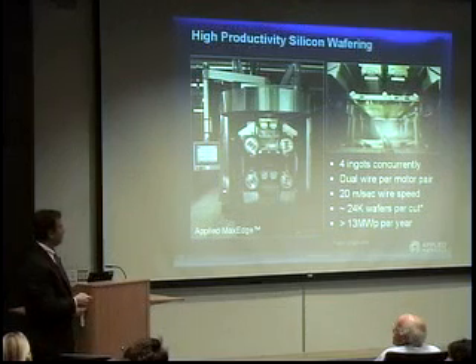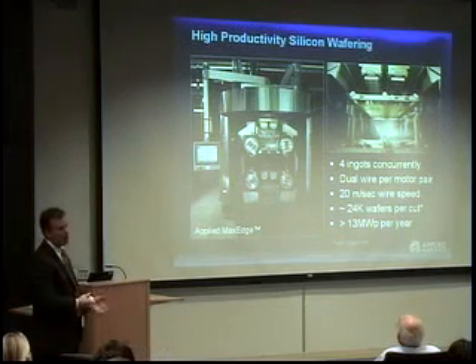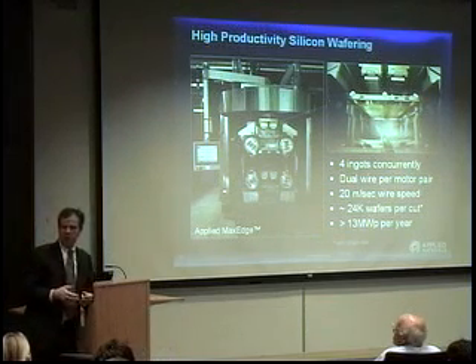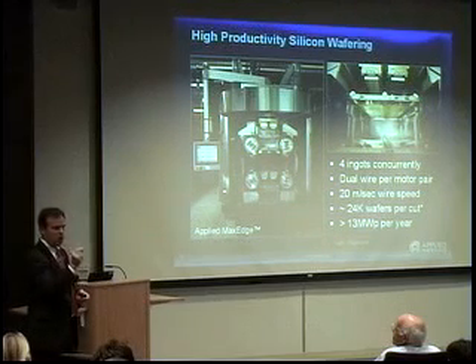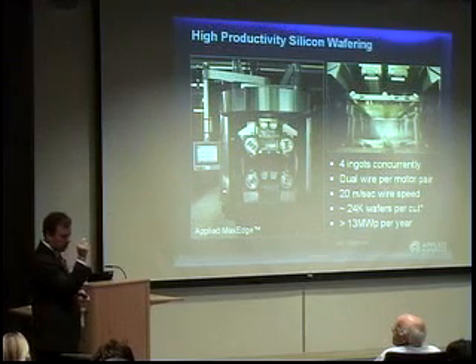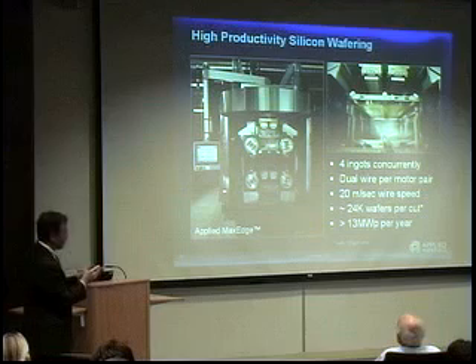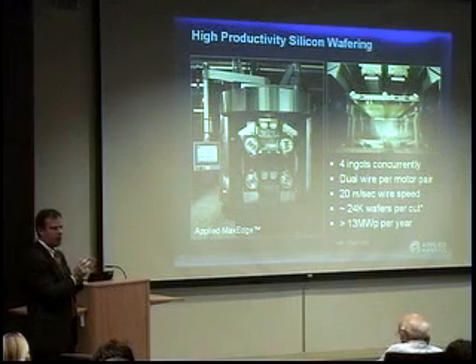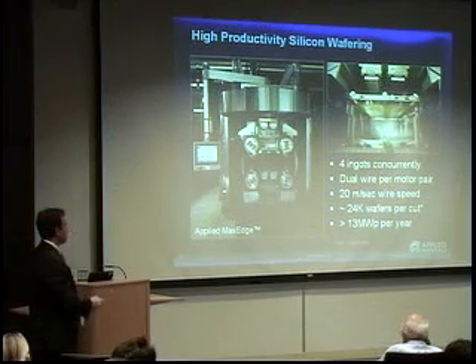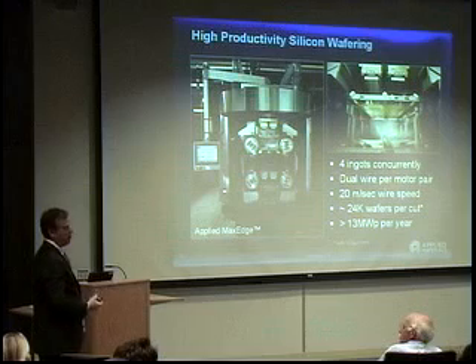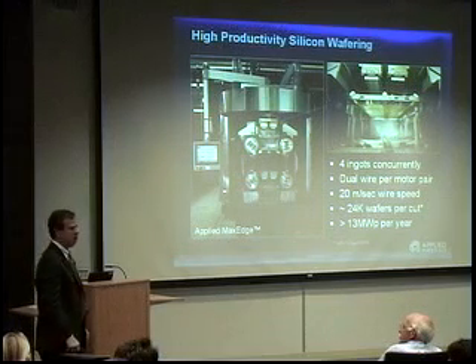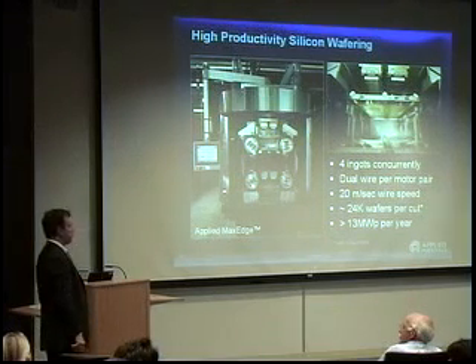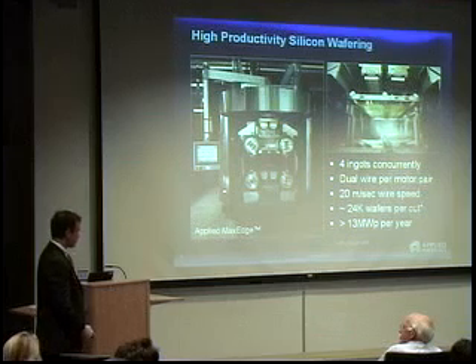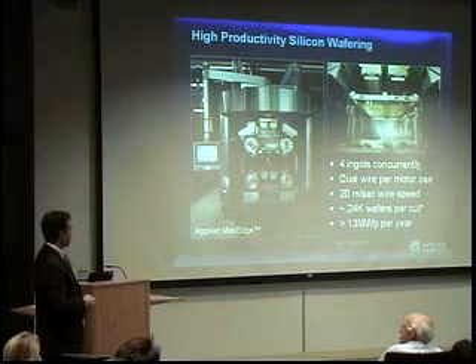And the idea here is that with this mesh of wires, and these wires are like what you have in a steel-belted radial tire, you waste as little silicon as you can by using a very thin wire, and you put the wires as close together as you possibly can to make the wafers as thin as possible. And we can make wafers now this way that are 100 microns thick, although in production today, most companies still use about 180 microns. So part of it is making the wafers thin.